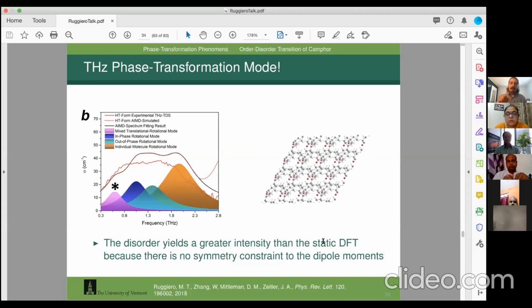But when you have a disordered crystal where every dimer is in its own orientation, and you have this motion, there isn't such a large net cancellation of dipole moments, which leads to a larger observed IR active transition. That's why the disordered crystal model does a better job predicting the intensity.